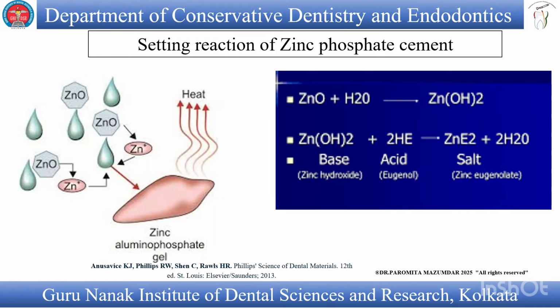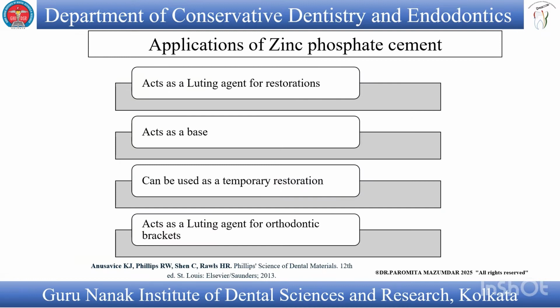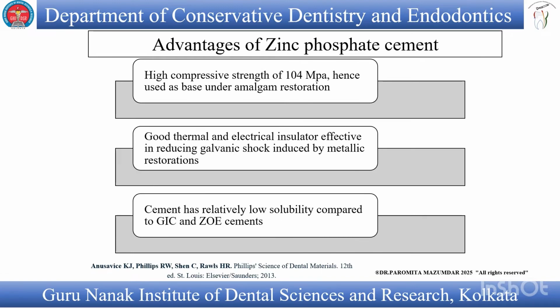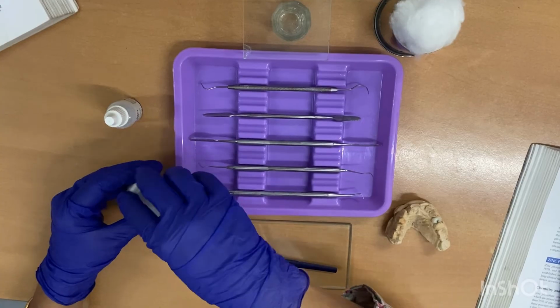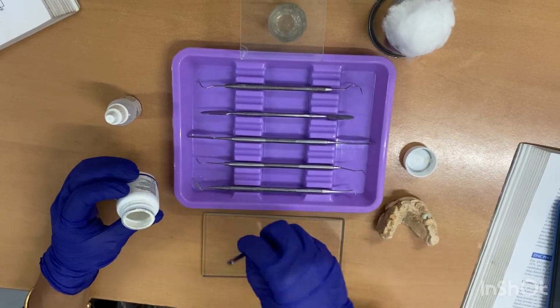For cementation, a film thickness between 20 to 40 micron is desirable. A ratio of 2 gram per 1 ml or lower is adequate to produce a film thickness less than 40 micron with a setting time of 5 to 10 minutes. With some cements, a film thickness of 30 micron or less can be achieved with a 1.6 gram per 1 ml ratio. A film thickness less than 25 micron is considered optimum for cementation of precision castings like inlays and crowns. But the consistency for use of this cement as a base material under fillings is usually thicker. Thus, a ratio of 2 to 4 gram per ml is usually adequate for this purpose, and it sets within 4 to 6 minutes.